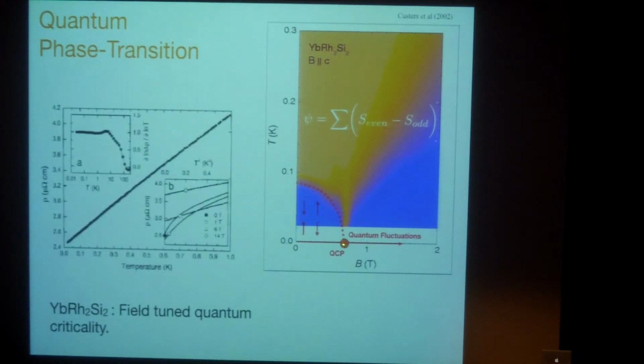One of the things that happens when you hit this quantum critical point, and this is the orange region, is it develops a linear resistivity. It goes from quadratic resistivity, which is blue, to orange, which is linear resistivity. And this is a sign of the breakdown of the Fermi liquid. And this linear resistivity extends up to quite high temperatures for this material, certainly up to 1, but maybe up to 10 Kelvin. And this kind of linear resistivity, or quasi-linear resistivity, is seen in many quantum critical systems. It's seen, for example, in quantum critical heavy fermion type systems. And we don't really have a good explanation for it. This upper temperature scale in the cuprates can be as high as 1,000 Kelvin. Okay? But one idea is it may be driven by quantum criticality.